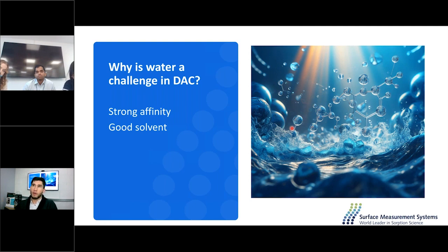For example, here we can take a case of carbonation-based CO2 capture processes, where an alkali or alkaline earth metal oxide reacts with CO2 to form carbonates, which is the basis of the process of calcium looping or enhanced weathering or cement curing. Water absorbed on the crystal surface and in the pores facilitates the carbonation process by dissolving some of the sorbent ions and some of the CO2. So it allows a kind of liquid phase reaction at the interface and speeds up kinetics.